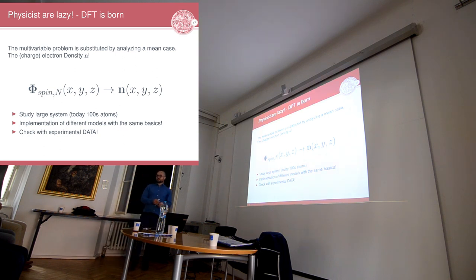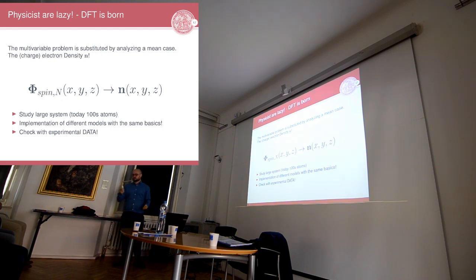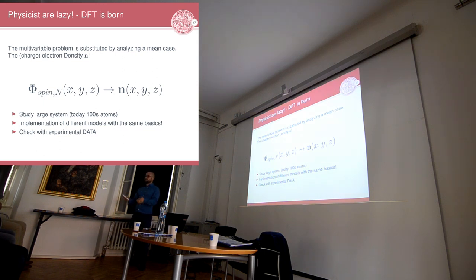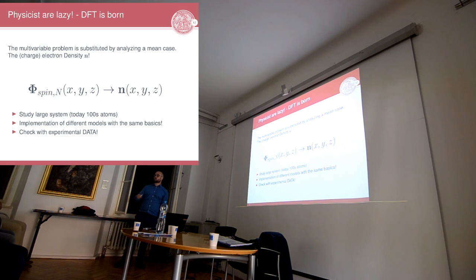The message behind density functional theory — DFT, as the name suggests — is: we can't really study the full wave function of electrons, so we simplify. We take the charge density — how the electron charge is distributed over space. This allows us to move from a 3N-dimensional configuration space to essentially three variables. There are methods that, once you calculate the density of a system, allow you to go back to the individual electron description and recover the properties you're actually interested in.